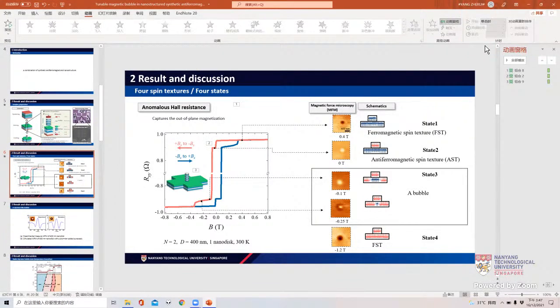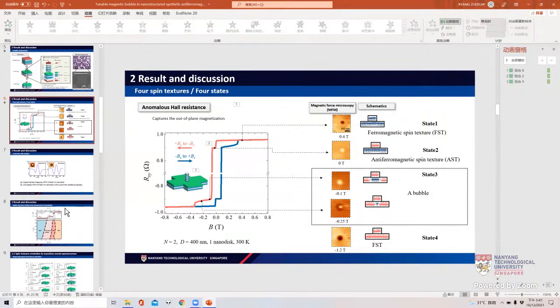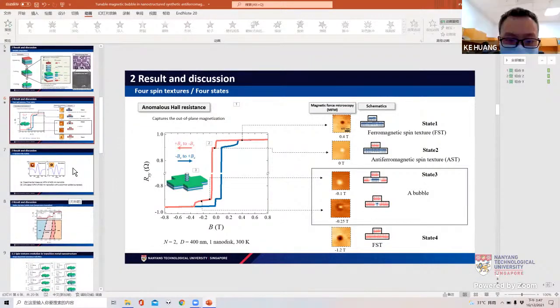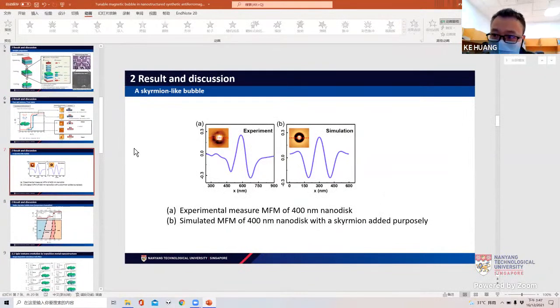Sure. So the only direct observation you have of the skyrmion is MFM imaging. Is that correct? Actually, we try to propose that it's like a skyrmion, but we don't have any solid characterization of the DMI. To my knowledge, if we want to prove that this bubble-like texture is a skyrmion, we need to estimate its DM interaction. But actually, in this work, we didn't. So we just want to propose it's a possible skyrmion. But currently our observation is the skyrmion-like texture via the MFM.